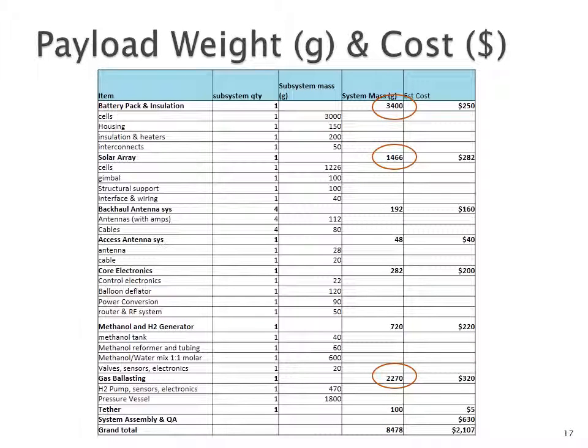When I look at the total weight of the system, the battery pack dominates. You've got batteries and insulation for the batteries, and on my system that's 3.4 kilograms, and a solar array of 1.5 kilograms, and those are driven again by electrical efficiencies. So driving down the electrical inefficiencies brings down your major weight drivers. The weight of the system feeds the volume of the balloon, and the volume of the balloon sets the amount of pressure vessel you need. So gas ballasting is another big one that falls behind the electrical efficiency.